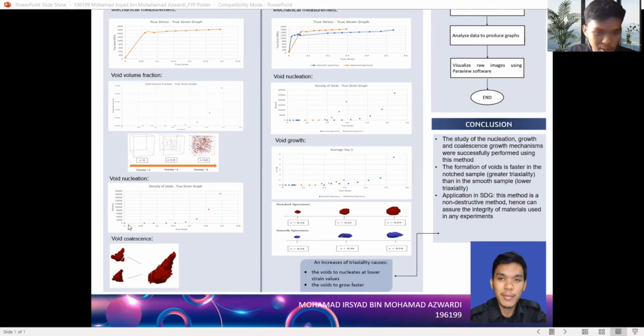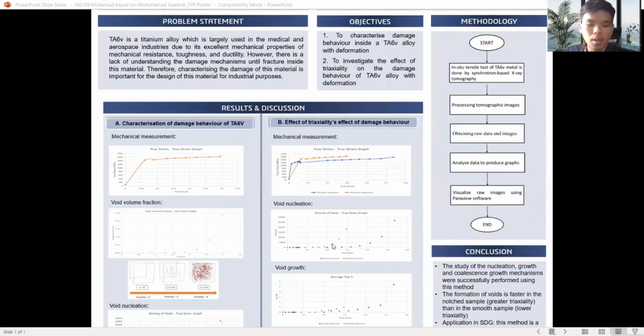So this is the void nucleation, which shows the increase of void nucleation along the deformation. And these are examples of void coalescence, where two different voids merge to form one big void. The next part of the results is the effect of triaxiality on damage behavior. For this part, the damage behavior inside specimens of two different geometries is compared. The first one is smooth and the second one is the notch sample. The smooth sample has a lower initial triaxiality compared to the notch sample.